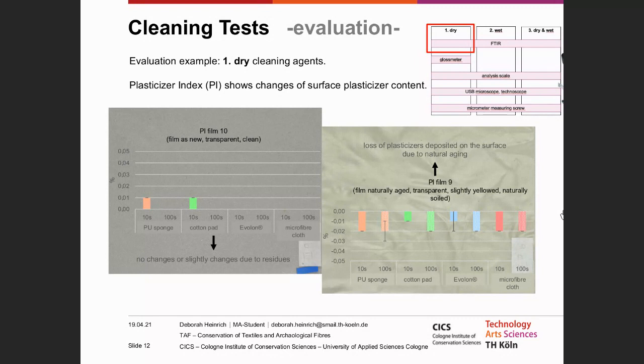The first test was carried out on 2 different PVC films, one as good as new, the other already slightly naturally aged. In the results, you can clearly see the difference due to this. The cleaning agents cause a decrease in plasticizer on the aged film. However, this is very small, less than 1%. Moreover, the results hardly differ in short cleaning time or long cleaning time. In the case of the new film, the plasticizer content on the surface remains unchanged. Individual small positive peaks are more likely to be due to residues of the cleaning agents.